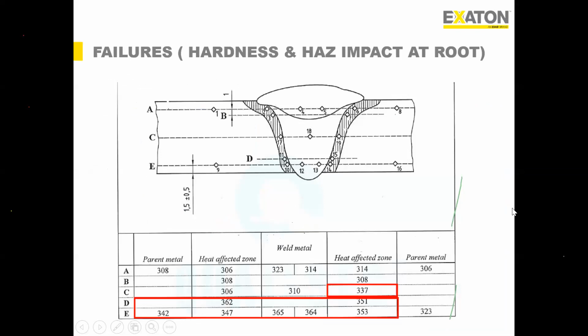So this is the hardness. So the hardness failure is interesting. The base material was duplex, where our recommendation was to go only the root with the super duplex, followed by the duplex TIG, and then followed by the duplex electrode. But the end customer wanted to make sure that we should not have any kind of corrosion failure. So what they did, they did the entire TIG welding with the super duplex, and the remaining was the electrode with the duplex. So it really passed the corrosion test, but there was a massive failure on the hardness.